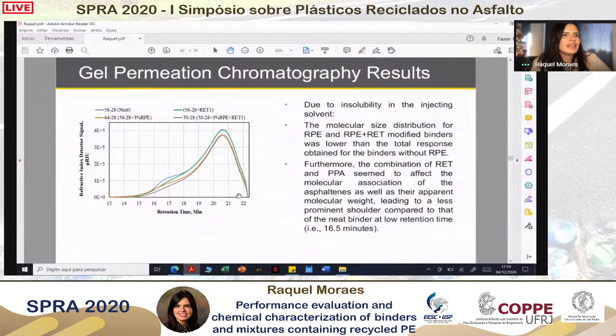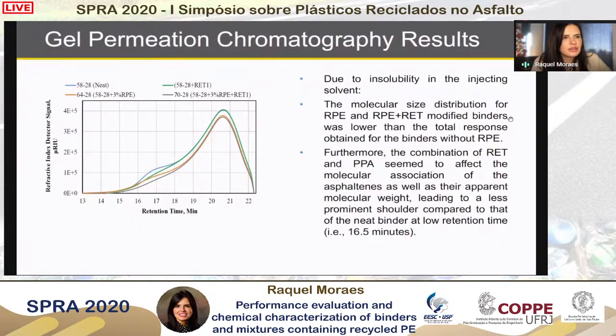Let me run. So as we can see over here, by the overall molecular size distribution curve, the modified binders are showing a lower overall molecular size distribution in comparison with the base binder, which we know is unrealistic because of the molecular weight of the polymer that is being added to the binder. So care needs to be taken when we're doing analytical analysis of material modified with recycled plastics, since the solvents that we use for evaluation cannot completely dissolve the recycled plastics.